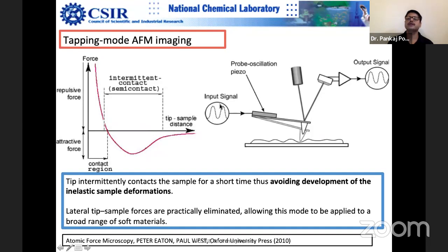What you would like to compare first is whether the amplitude is the same. For example, this is the free amplitude when the tip is far away from the surface. You know the free amplitude, so you have recorded that. This free amplitude is in fact controlled by the signal strength. And then you know what the phase is. For example, when this signal is peaking here, this signal should also be peaking here. If it is somewhere here, that means there is a phase difference. And the third thing is the frequency. Suppose this frequency is a few kilohertz. You can check whether the signal is coming at the same frequency.